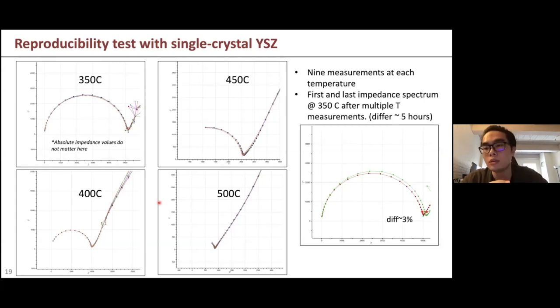In the end, I purposely prolonged the measurement time. Here on the right side, this is the spectrum under the same condition at 350 C, but between them there have been a lot of measurements, and it has been around 5 hours. In the end, however, the impedance only differs by around 3%. So I would say the reproducibility of this device at high temperature is very, very good.